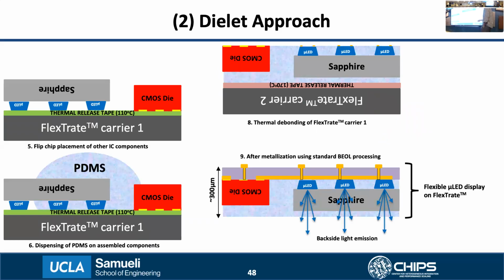In this case, we would get a display that is not as flexible as in the mass transfer case, because it still has a rigid sapphire dielet. But it would still be flexible because of a so-called bicycle chain concept, wherein you would still have the sapphire dielets separated by PDMS between them, and that makes the system reasonably flexible. But in this approach, the light has to first pass through the sapphire and then the PDMS, and then it comes out from the backside. You may want to mention why this approach was used, because of transferring the wafers to Japan and back. Yeah, I'll talk about that later.